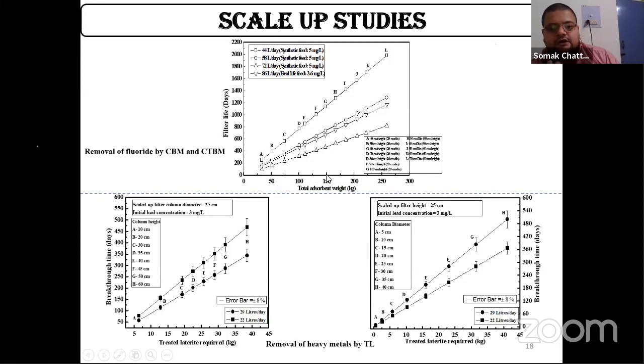So if you see for 150 kgs, for example the point G, which is 100 centimeter height and 20 centimeter diameter, 150 kg material will have a filter life of around 1200 days. So basically around 4 years. Similarly, we can do the same thing for lead removal as well.